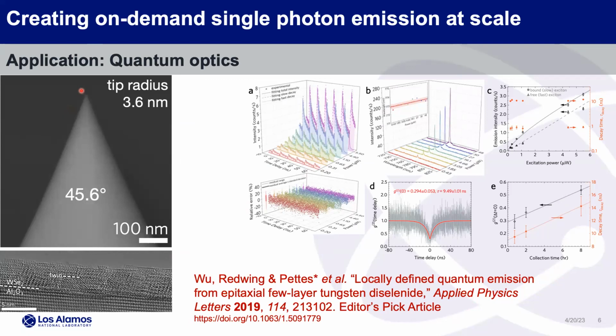So this is epitaxial tungsten diselenide. We got the material from Penn State, from John Redwing, and there are twins in the material. It's disordered. It's not monolayer. The new samples they give me are monolayer, but this one, when they were setting it up, is not monolayer. It's pretty thick. It has emission at about 1.5 electron volts, and it shouldn't be able to be changed by strain.